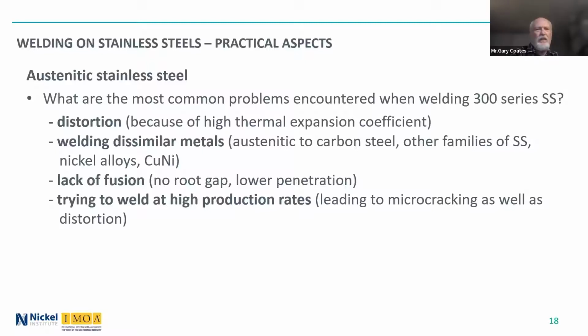There are things like, you need more tacks when welding together plate, and you need to use a lower heat input. The high heat inputs will cause more distortion than the lower heat inputs. A number of factors come into it, but distortion is the number one issue I see that people face.